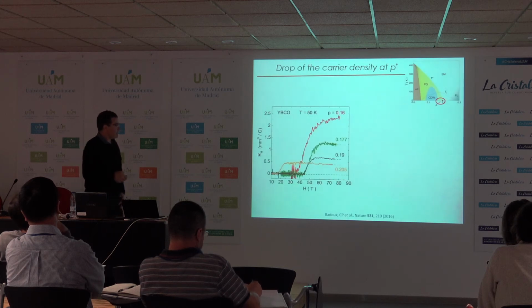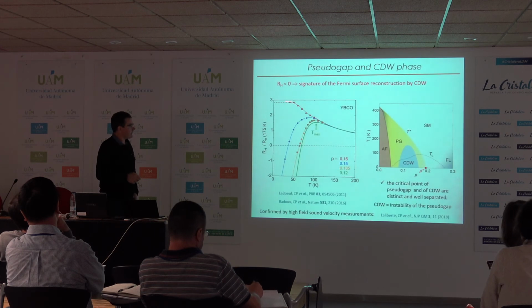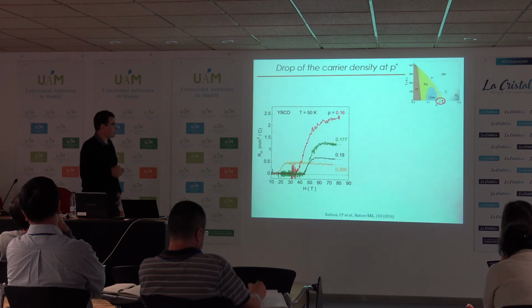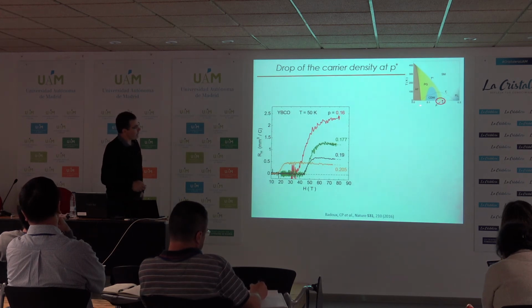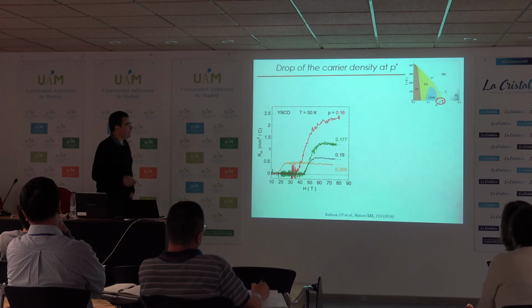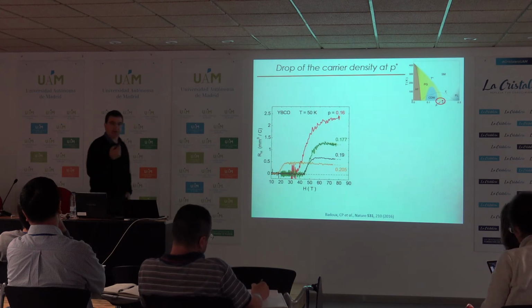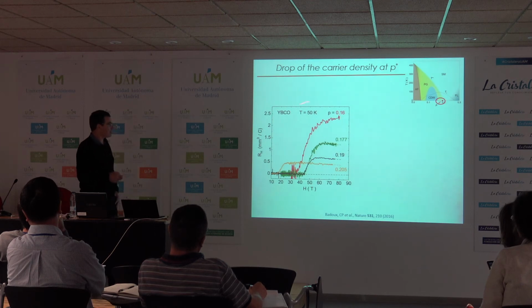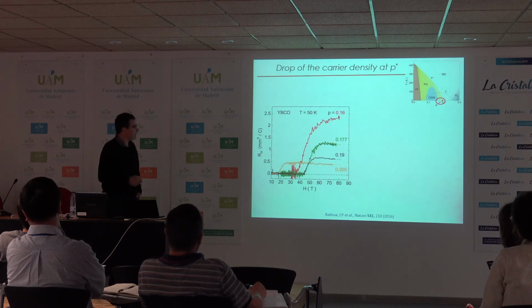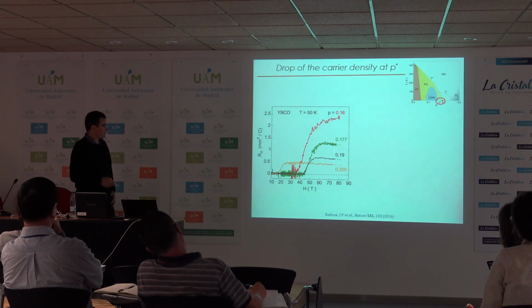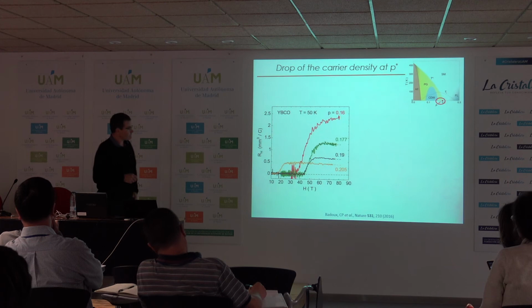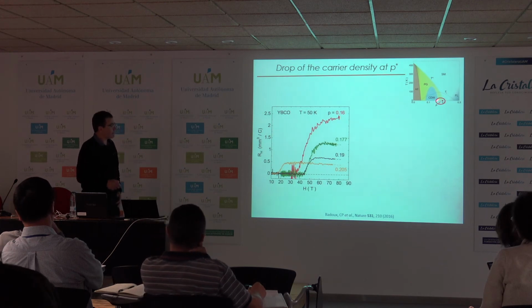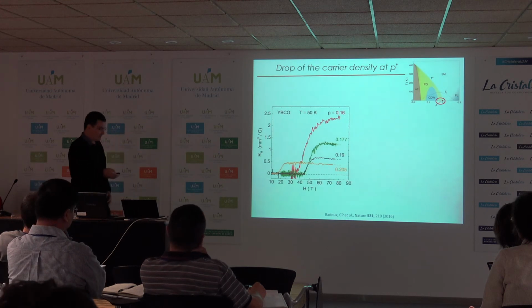So when we saw this result in the 16% YBCO sample, we decided to go and make some measurements through P-star, the critical point of the pseudo-gap. Of course, the critical field in this doping range is high, so we don't have very low temperature measurements, but here I show you some Hall effect measurements versus magnetic field up to 80 Tesla at 50K. What you can see is that the Hall effect remains positive at all these dopings, from 16 up to 20%. P-star is believed to be 19% in YBCO.